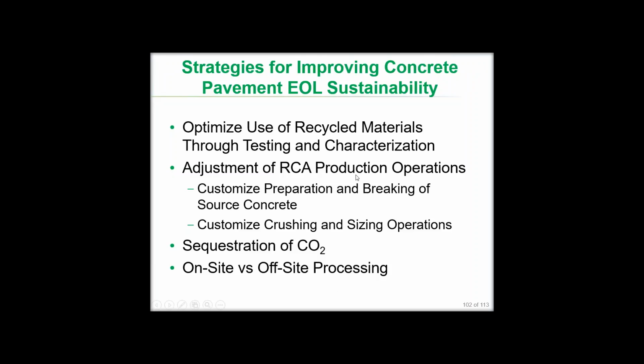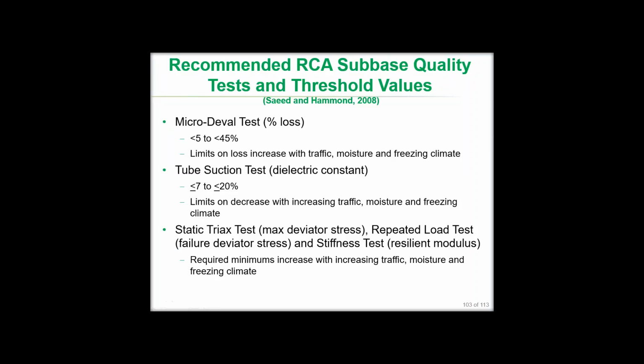So again, there are the four major headings here, and an example of additional testing. Besides the testing for D-cracking and testing for ASR and testing combinations of those materials for use in concrete mixtures, there is also some guidance that was developed by Attar Saeed and Mike Hammond under an NCHRP study about 6 or 7 years ago, I guess, for better use of RCA in subbase applications. And they developed a table that provided guidelines with a series of test requirements using the micro-Deval test for abrasion resistance, the tube suction test, and a number of stress tests: triaxial test, repeated load test, and stiffness test, resilient modulus.